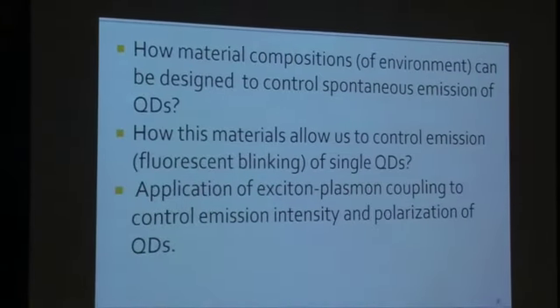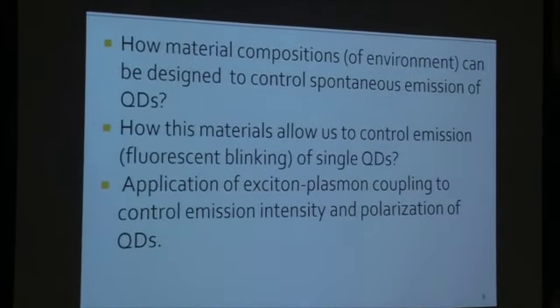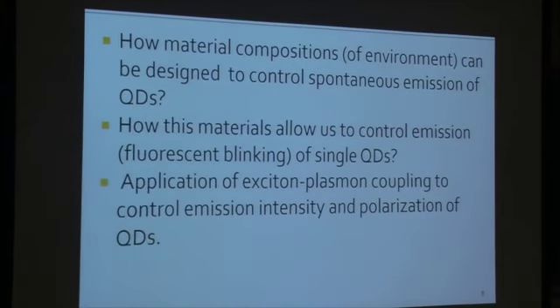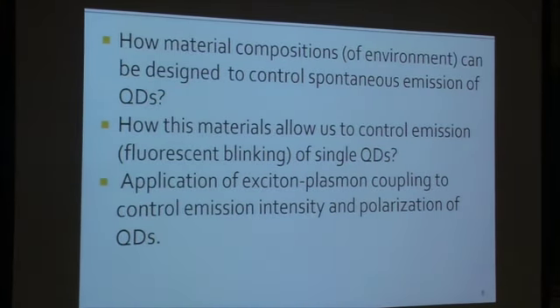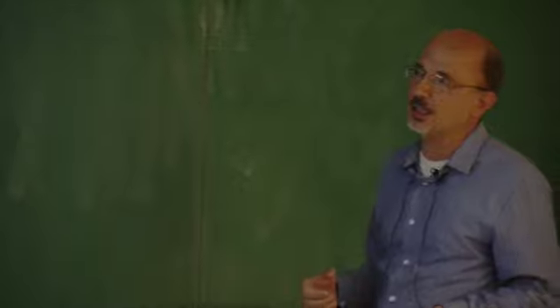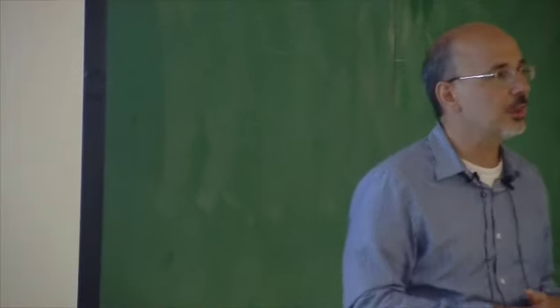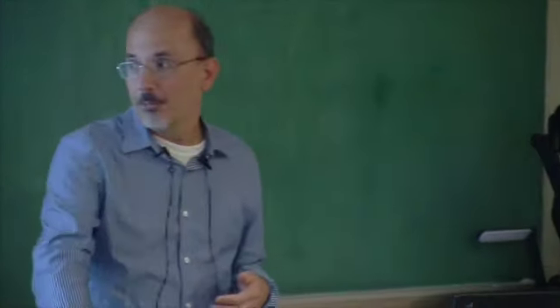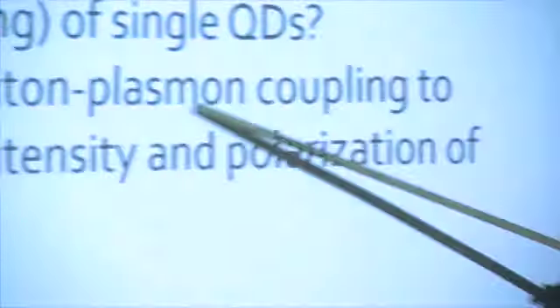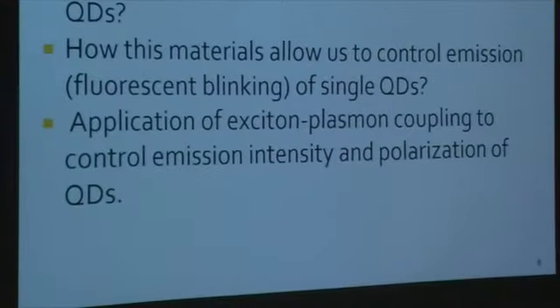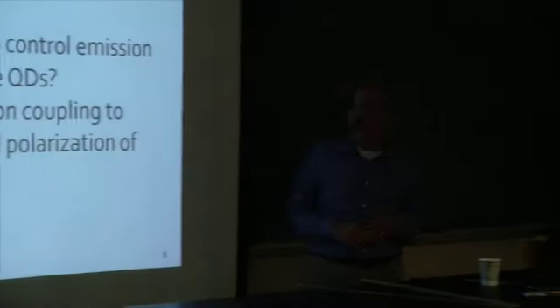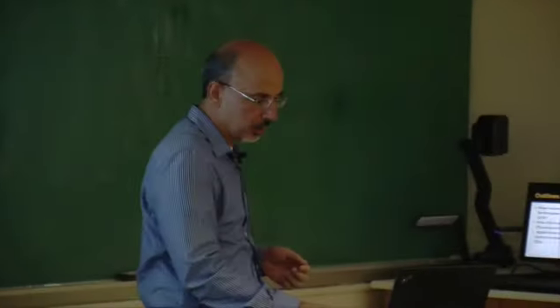When they become single quantum dots, the rules change a little bit. Probably you have heard about quantum dot blinking, or fluorescence blinking of the quantum dot. The question is how we can control that blinking. And as I showed you, by changing the material, you can change it quite dramatically. And then I go towards the application of exciton-plasmon coupling to control the intensity and polarization of emission of the quantum dot.